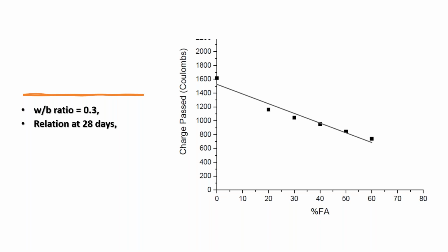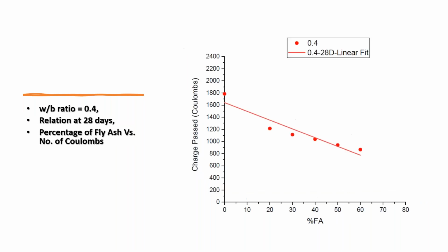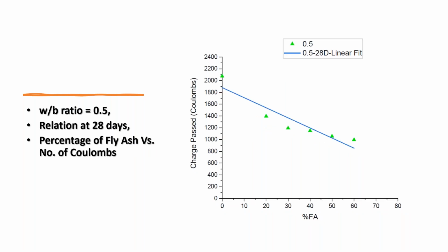Yeah, we are doing some work here now. You can see this graph, this is water binder ratio 0.3. On the x-axis is percentage of fly ash, on the y-axis it is the coulombs. You can see as the percentage of fly ash increases, the number of coulombs got reduced. This is in the case of water binder ratio 0.3 at 28 days. So this is the relation for water binder ratio 0.4 at 28 days, with different percentages of fly ash. And this is for water binder ratio 0.5 at 28 days and for different percentages of fly ash.